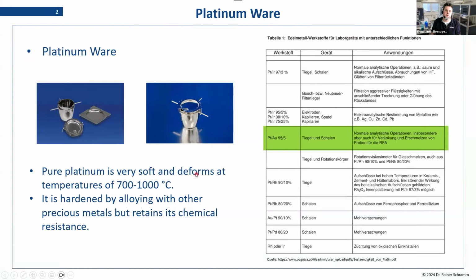Pure platinum would usually be too soft, especially if you use the platinum ware in a process with high temperatures, because pure platinum would deform at around 700 to 1000 degrees centigrade. That means a crucible would not be stable. It would start to deform and bend. So the manufacturers alloy the platinum with other precious metals. That gives it mechanical stability. It hardens the piece that you are using, while retaining all of the chemical resistance that platinum offers, which makes them so desirable as a vessel.